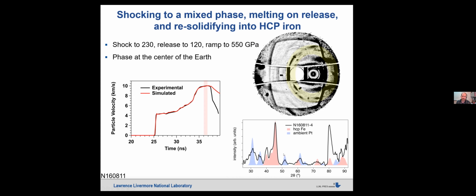And when we take a line out over the entire stereographic projection, what we've seen is in this region, you see the HCP triplet here, although it's not as refined in the lineout, because what we've done is we've added, shown in the light pink here, instrumental broadening. So we would expect to see this type of instrumental broadening for an HCP triplet. And if you even look at the data, you can actually track and see the HCP triplets, even though it's slightly textured.